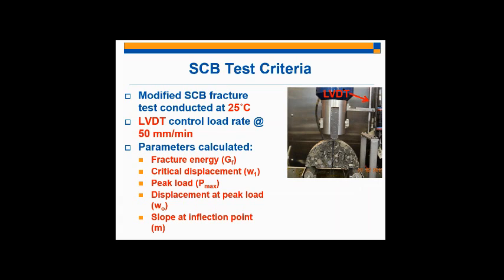So after a screening of different displacement rates, ranging from 6.25 to 50 millimeters per minute, we've selected the optimal displacement rate of 50 millimeters per minute. And this provides the best variability, the best distinction, and the best results from the test. So the parameters that we calculate from this test are as follows. You have the fracture energy, which is typically what's calculated in the classic low temperature SCB test. You have the critical displacement value, W sub 1, and I'll discuss all of these on the next slide.